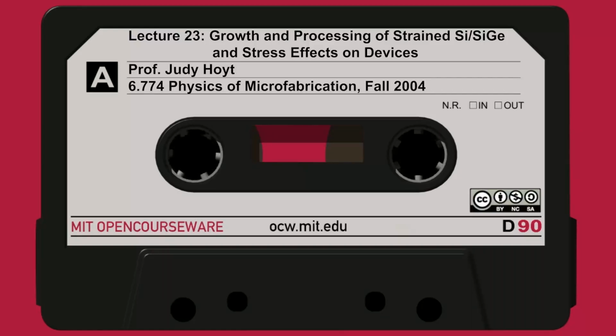This is just a cartoon. It's actually been demonstrated fairly recently here at MIT, on page 44. In fact, this is the process that was used. A very complicated stack of epi layers was grown, but the important thing is the top of the stack was strained silicon, and that whole stack was bonded to an oxidized silicon wafer, and then everything was removed by selective etching. So when you're done, all you have left is strained silicon directly on the oxide, and you use etch stops between the top layers, so you can etch back the entire wafer and just leave strained silicon behind.